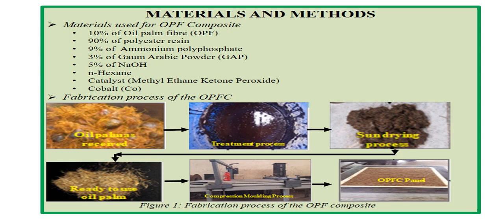The panel was obtained by first preparing a mold, and then the internal area of the mold was applied with a release agent, Vaseline, while the ready to use oil palm fiber were then randomly distributed in the mold, ensuring that there were no voids. A paste of resin and the flame retardants, in addition with the catalyst and the accelerator cobalt, were then mixed properly and poured over the oil palm fiber in the mold. This is the final product of the oil palm fiber composites that was obtained after the process.